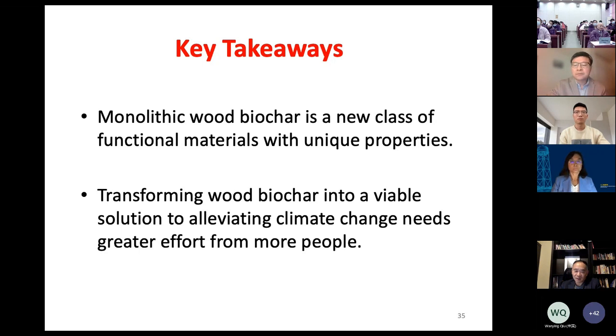Another important property is the density of the biochar. For example, African ironwood is very dense, right? And dense is good in the sense that your device will have a smaller volume. But on the other hand, if the structure is too dense, the internal structure may not be so accessible. Our preliminary results indicate that the maple, which is very common in Canada, is among the best. Okay. Thank you so much.